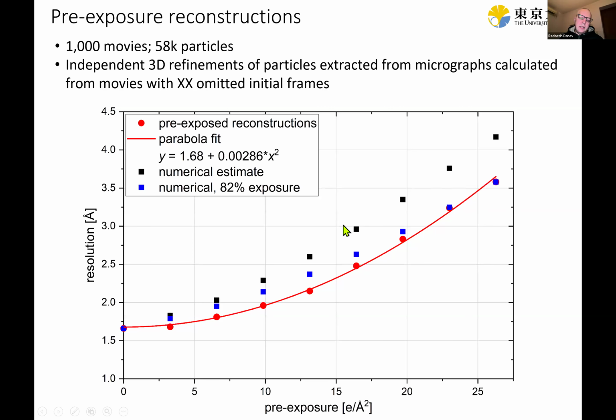Now, what is interesting here is that in the model, the damage starts from the beginning. So basically the next point is already at a noticeably lower resolution compared to what we see in our experiment. By removing the first 5 frames, we didn't see a big change in resolution, which would mean that maybe there is still some motion there that affects the initial frames. So they are not fully contributing their information to the reconstruction. So that's something to consider in practice.